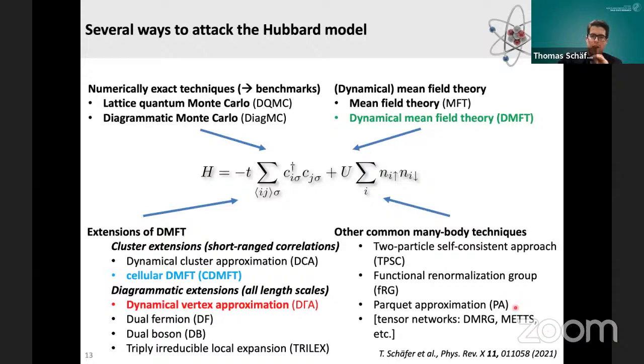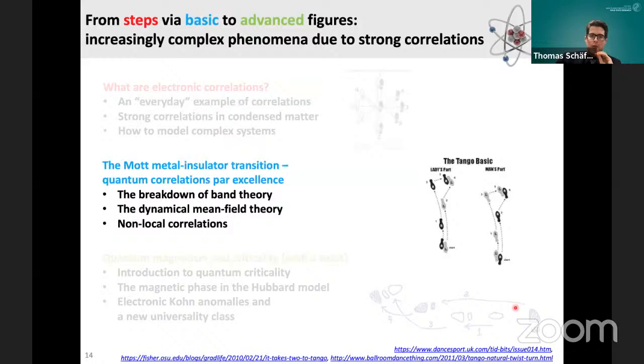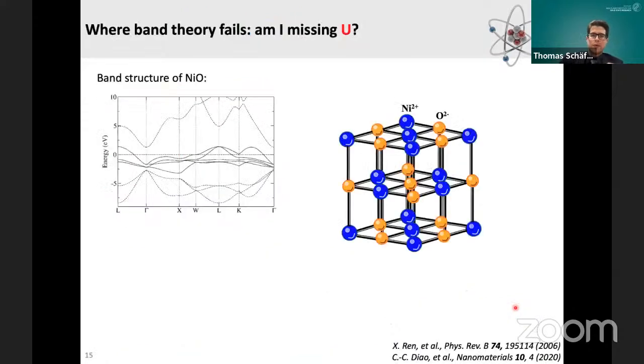model systems numerically. And I will now show you a first example of an effect, which is really a quantum correlation effect par excellence, namely the Mott metal-to-insulator transition. For this, we switch to a different material, namely nickel oxide, whose crystal structure you can see on the right-hand side. For this compound, we can do a so-called band structure calculation.